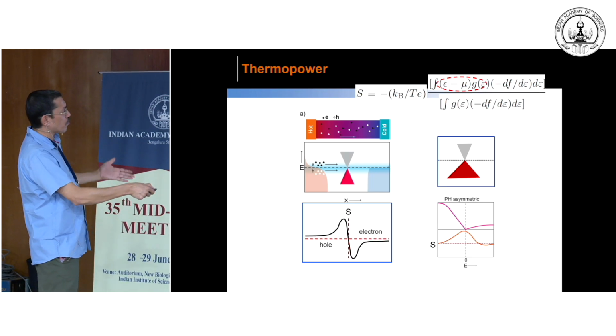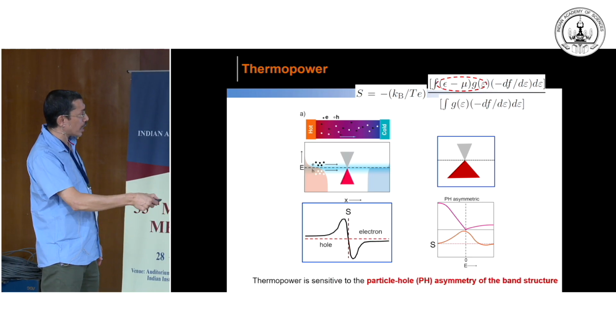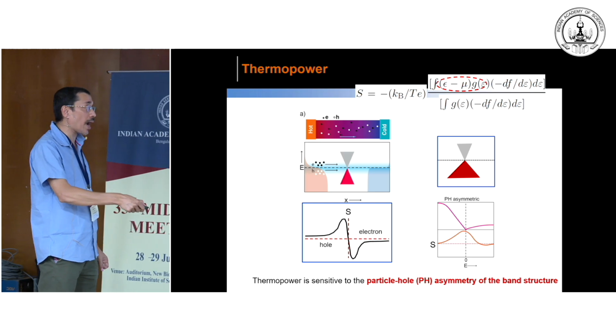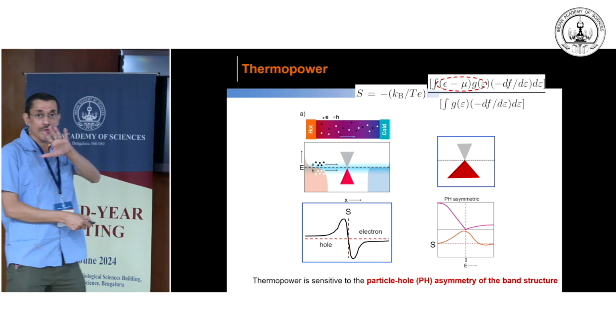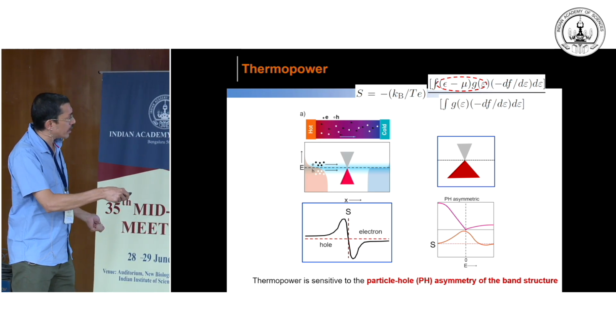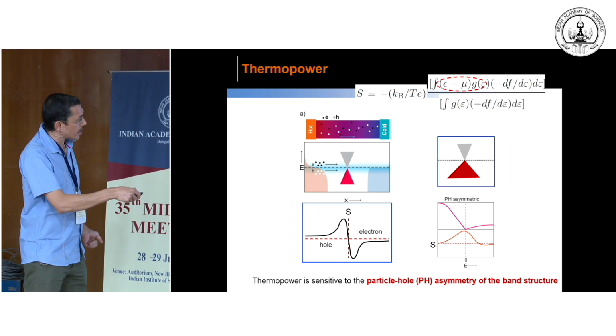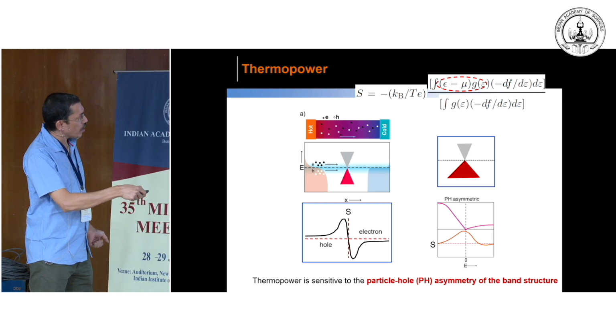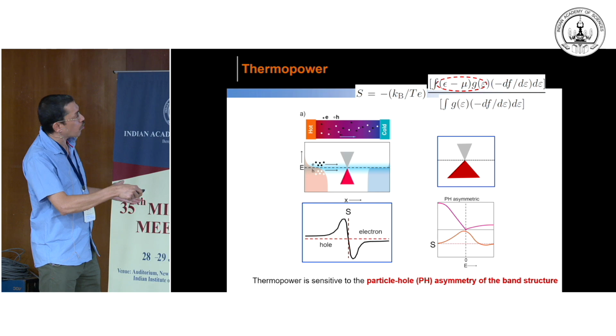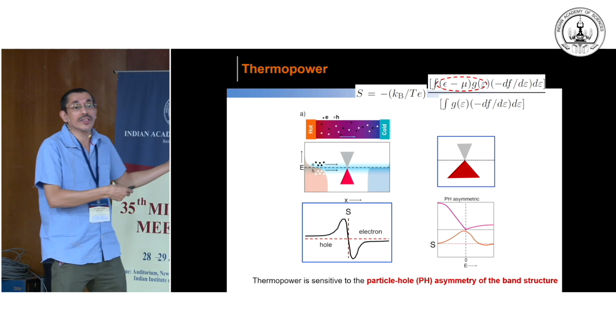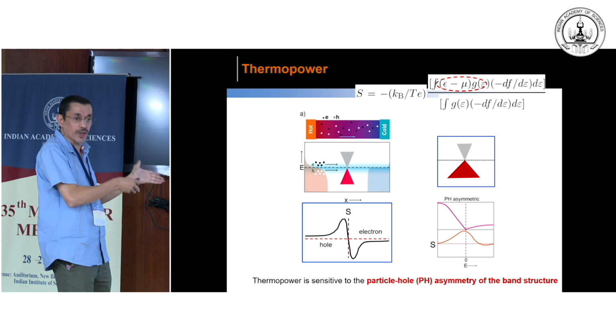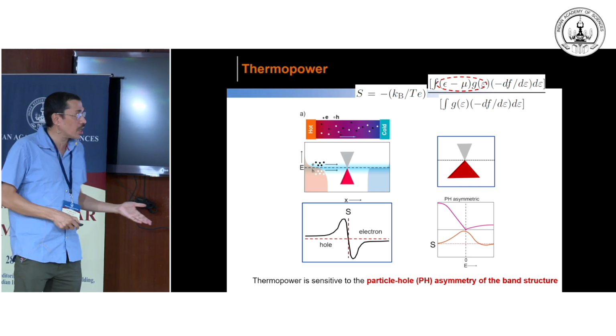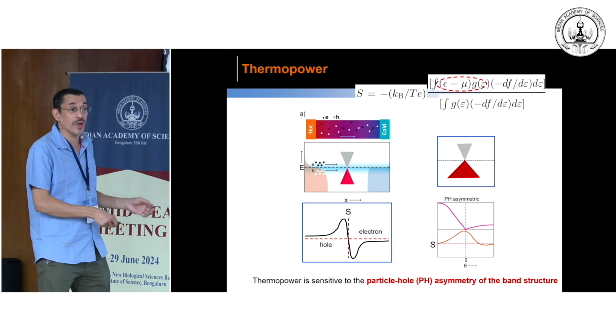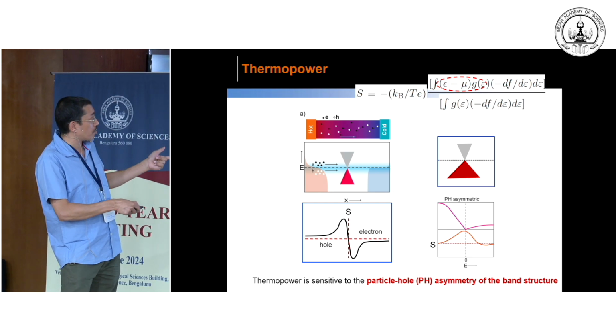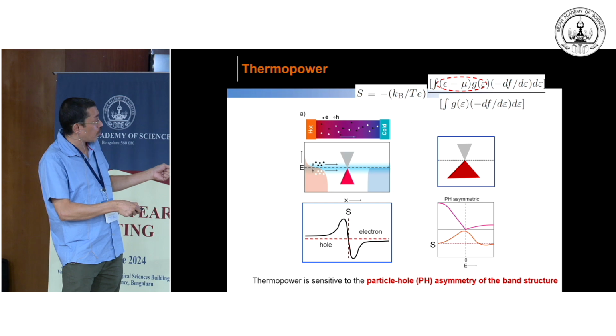And just to give you more overview, without going into details, the thermopower is highly sensitive to the particle-hole asymmetry of the band structure. Just to give you a physical picture, what does it mean? For example, at the Dirac point, you have both electron and hole type carriers, because that's a particle-hole symmetric point. If you have a hot and a cold end, both electrons and holes will move from the hot to the cold end, but this will not give me anything, because both go from one end to the other, and the resultant thermoelectric voltage will be 0. So this is exactly what has been seen: at the Dirac point the thermoelectric voltage will be 0, but if you go to one side where it is more electron-like, the thermopower will be negative, and if you go to the hole side, that will be positive.